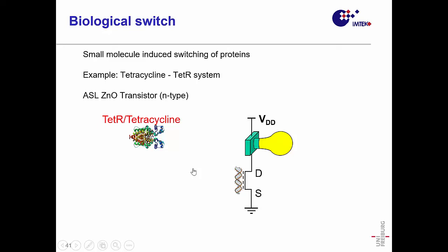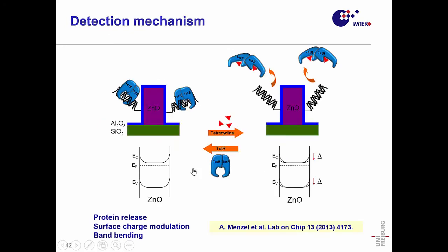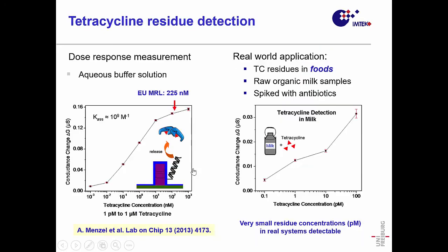That means you have a signal. Okay. So we did that, and because it's zinc oxide, which is very often not stable in electrochemical settings, we put some aluminum oxide on top of that. By modulating the surface charge, you have a bending, and so you can release that.